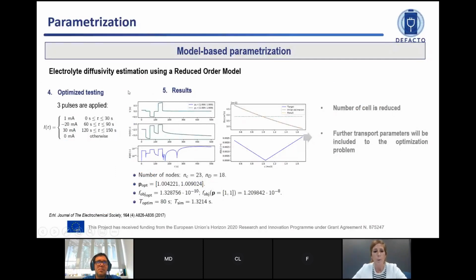And then what we've been doing is that we can run experiments, but we can also run simulation with a synthetic test. So in this case, we took the literature data for the electrolyte diffusion coefficient, and we know which pattern it should follow, which is the blue line below the red one here. So this is the target. We need to identify exactly this pattern for the electrolyte diffusion coefficient.